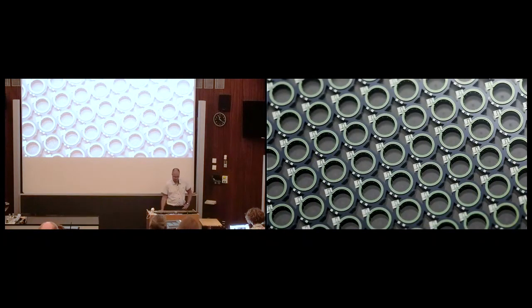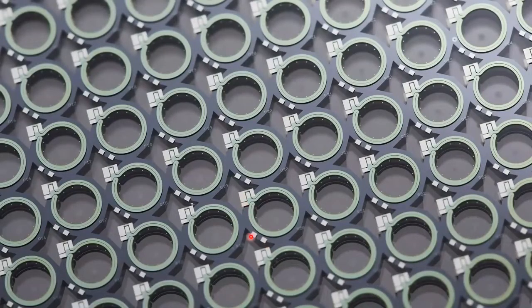Here we have a close-up of this wafer, and you see here quite well the resistive heater. One loop going back and forth with some contacts, because the backside also has to be contacted afterwards. And here you have the contacts to put the NTC temperature sensor on it. You see also quite well here these gold discs, but again they are not on the same surface as the metallic pattern, but they are inside the cavity.